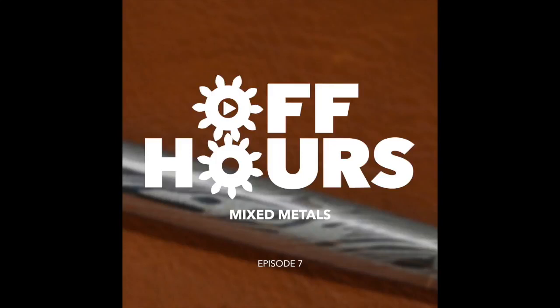Well, the big one is not getting a complete fusion weld, and the trick with it is that you have to get the right temperature, and you have to get the right force, because you need the pieces of metal touching completely. Like you need a complete surface contact between the two pieces. You can't have anything in between them, so they have to be perfectly clean. Again, degreasing and being very careful about how you touch the plates.